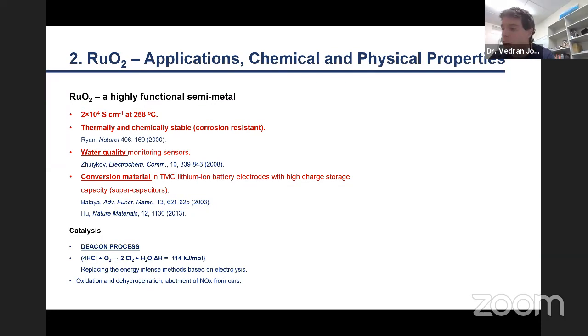And now there are hints that the functional catalytic properties can be related to specific niceties of the Fermi surface. For instance, first principle calculations actually believe that these magnetic moments are responsible for many of these catalytic applications. And such magnetic moments are actually confirmed by neutron scattering, and they have been attributed to the spin density wave instability driven by particularly large density of states at nested hotspots in the Fermi surface, which I will show you.